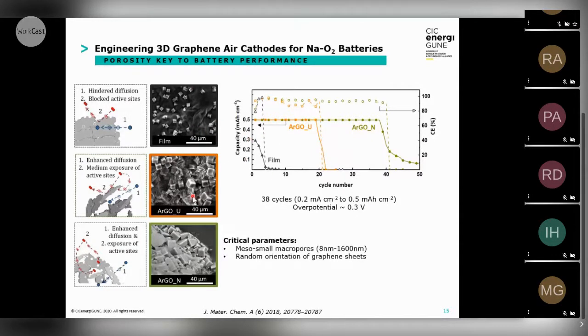Then when we go to the second sample, we can see that the diffusion is enhanced. You have some seeds, some one on top of another, but others forming some kind of 3D structure. So in this case, the oxygen diffusion is enhanced, and you have a medium exposure of the active sites in order for the oxygen to be reduced. And in this case, we can increase the cycle life to 20 cycles.